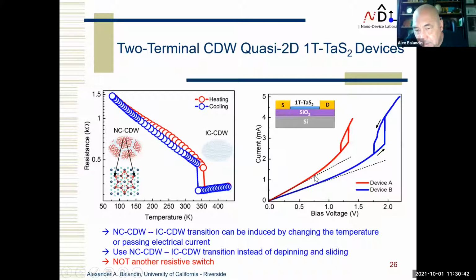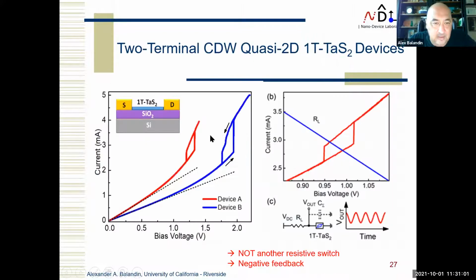You can also see there is some onset of superlinearity here. And as we discovered, we explained it, proved it now, this is not onset or sliding of charge density wave. This is actually local heating. Okay? But now can I do device functionality? My idea was, if I put the resistor in series, I put the load line, it goes through this hysteresis, then I can get oscillations, quite a stable thing. This is like negative feedback.